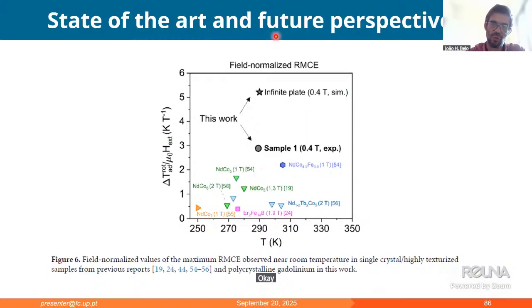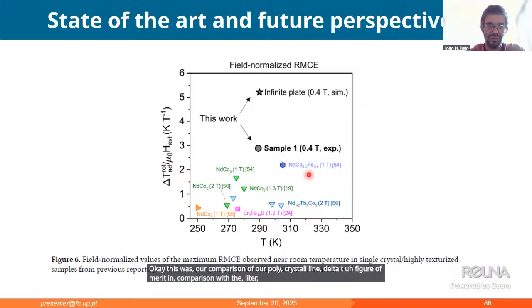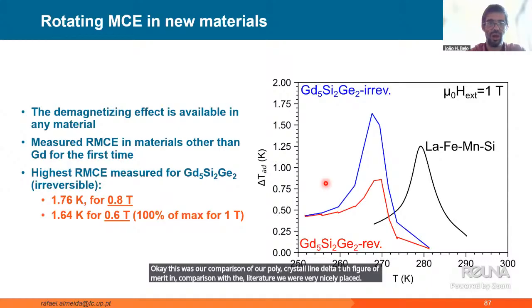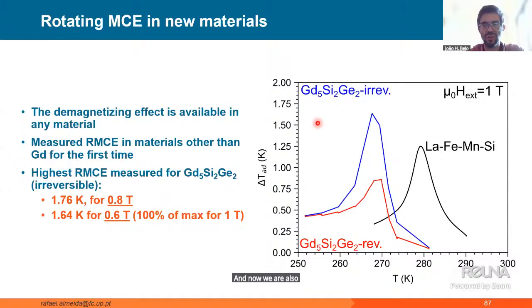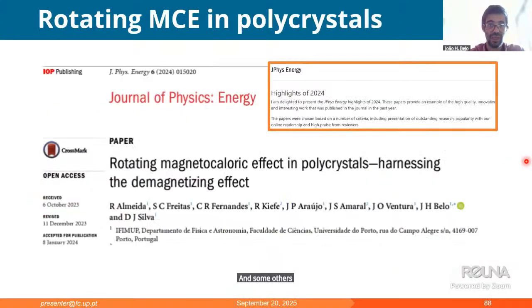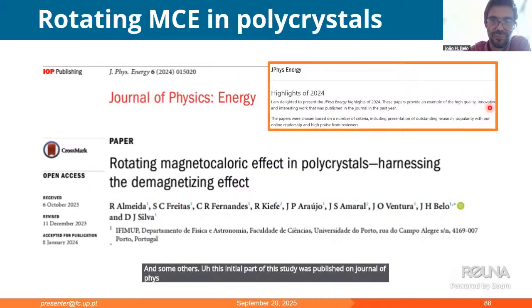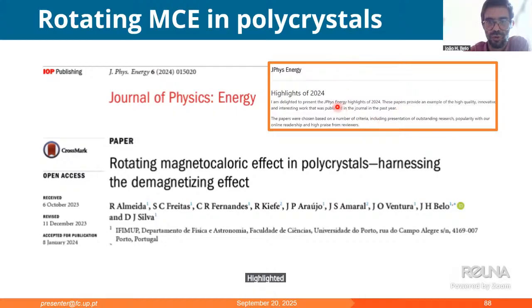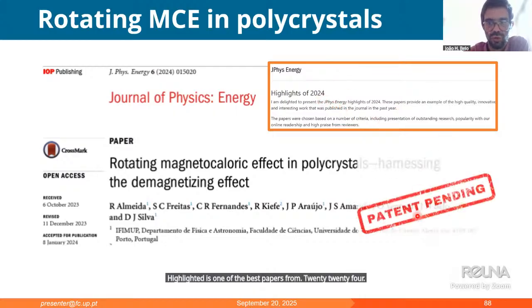Okay, this was our comparison of our polycrystalline delta T figure of merit in comparison with the literature. We were very nicely placed. Now we are also studying other conventional magnetocaloric materials upon rotation, like gadolinium 5 silicon germanium, but also lanthanum iron silicon and some others. This initial part of the study was published in Journal of Physics Energy, highlighted as one of the best papers from 2024, and these major results are also under patent pending.